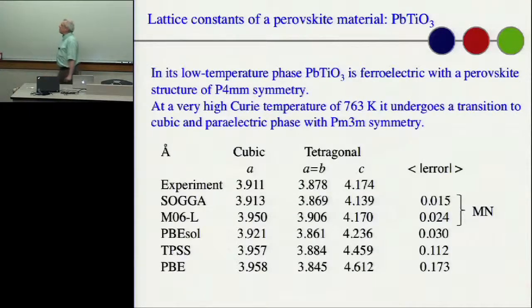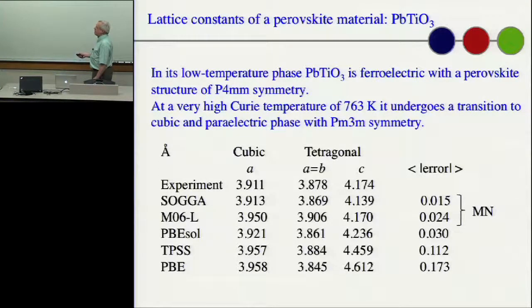Here's one that I wanted to show. I thought it might be of interest to this group. Lattice constants of a perovskite material, lead titanium trioxide. In its low temperature phase, it's ferroelectric with a perovskite structure. And then it has a fairly high, unusually high Curie temperature where it goes to the paraelectric phase, which is cubic. So here we have experimental data on the lattice constants for the cubic and the tetragonal. The tetragonal is this one here, the low temperature one.